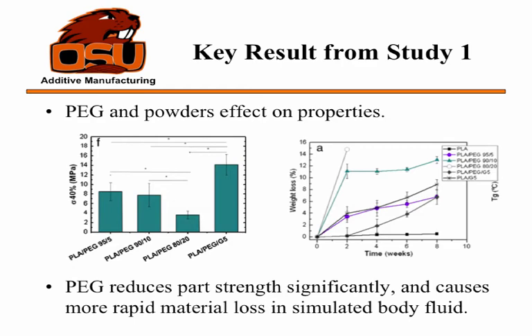And on the right there, it is a graph of time versus weight loss in a simulated body fluid. And you can actually see that adding PEG increases the speed at which weight loss occurs, because PEG is actually water soluble and will disappear very quickly. And then if it's just the PLA with a little bit of additive, almost nothing happens over the course of 8 weeks. So they could get an idea of what you would need to make it biocompatible and how you could adjust its properties to fit the application that you're using it for.